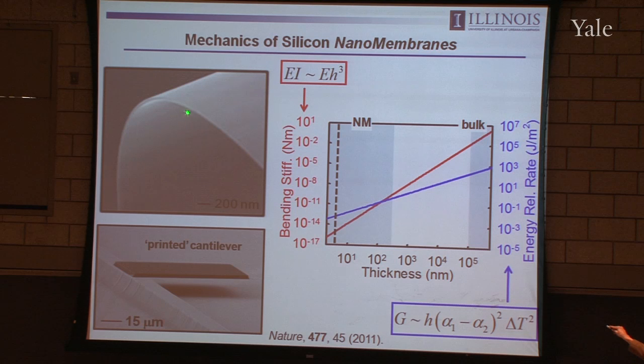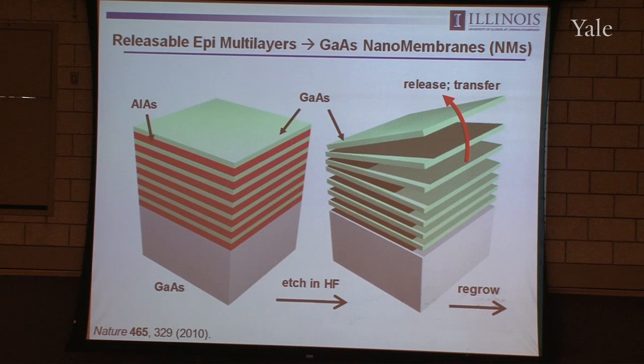So it's floppy, that means you can bend it. It's sticky, which means you can take the silicon and put it onto a bendable substrate, like a sheet of plastic, and not worry too much about interface adhesion by virtue of this linear scaling down in the energy release rate associated with crack formation. So those are the interesting aspects of ultra-thin sheets of a material like silicon.